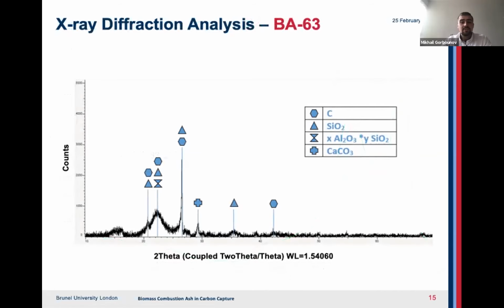We have additionally run the XRD analysis on it, and the results are presented on this slide. The main peaks visible in the figure have been attributed to the presence of crystalline carbon and, to a lesser extent, crystalline silica, which is in good agreement with the information gathered from previous analysis. And the broad peaks on the left have been ascribed to amorphous carbon, quartz, and mullite, and the peaks on the right from the main peak denote the presence of calcium carbonate and some more quartz.